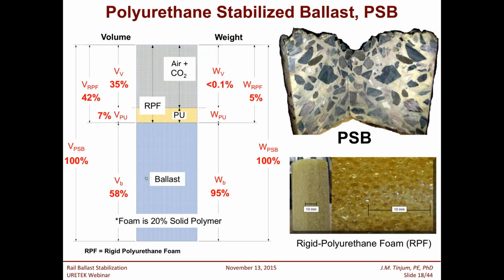So what is polyurethane stabilized ballast? It is a chemical grout, as was discussed earlier, which is injected into that ballast or subballast system, and basically it takes up the void space. As far as a phase diagram, you see that the polyurethane product itself may be about 7% of the overall volume. That can give you an indication of the chemical costs and application costs for this material. Look at the lower right corner. You can see that honeycomb structure of rigid polyurethane foam. That's what it looks like under the microscope, and we saw a cut-open ballasted section in the upper right corner to give you an indication of what this looks like.